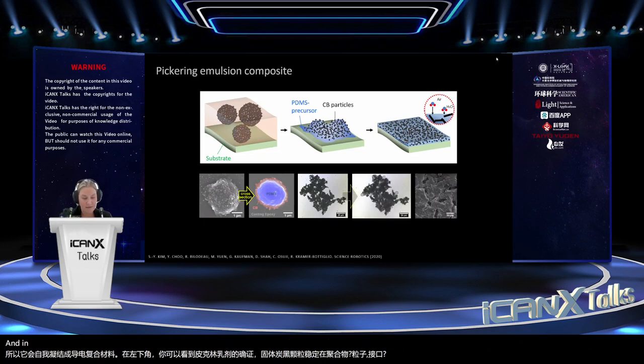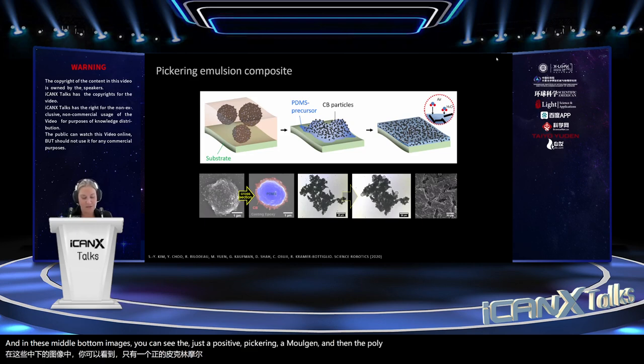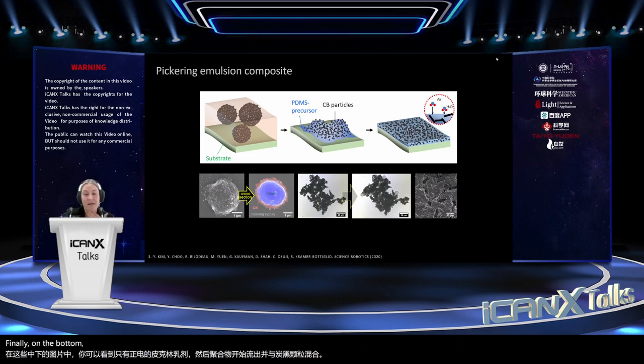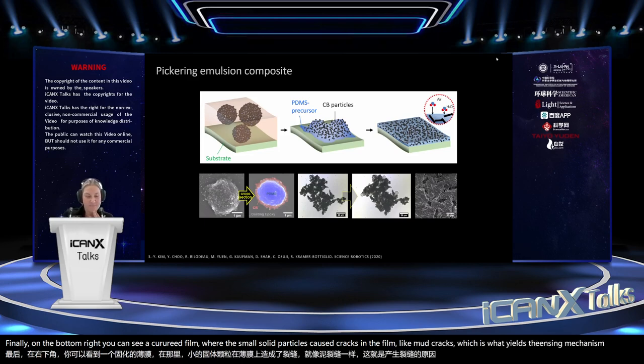And in these middle bottom images, you can see the just deposited Pickering emulsion and then the polymer starting to flow out and mix with the carbon black particles. Finally, on the bottom right, you can see a cured film where the small solid particles cause cracks in the film, like mud cracks, which is what yields the sensing mechanism.